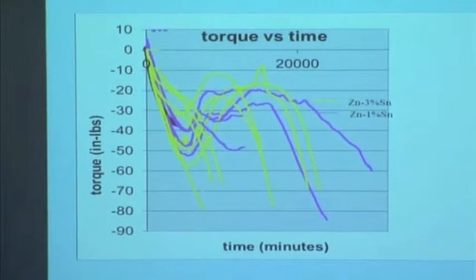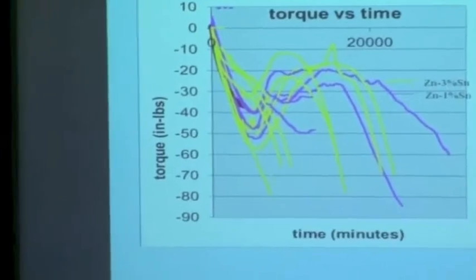We have a hypothesis, which is that these columnar crystals, iron again and zinc here, are hexagonal close packed, and there are relatively few slip planes in hexagonal materials. That is, it's fairly difficult to move these materials. And you need 5 independent slip systems to accommodate any arbitrary deformation. That doesn't exist in these columnar crystals that have this structure. And so as a result, our hypothesis is that it begins to get harder and harder to deform this material. Now, we need to do more work to confirm this.